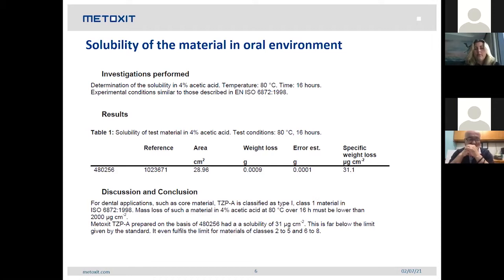And also a very important fact, and I'm not sure if many companies do this, because there's no good publication for a lot of manufacturers. So you have to take care of the solubility of the material in the oral environment. In the patient's mouth there's an acidic oral environment, and you have to make sure that the zirconium oxide you use in your CAD/CAM blank is stable.